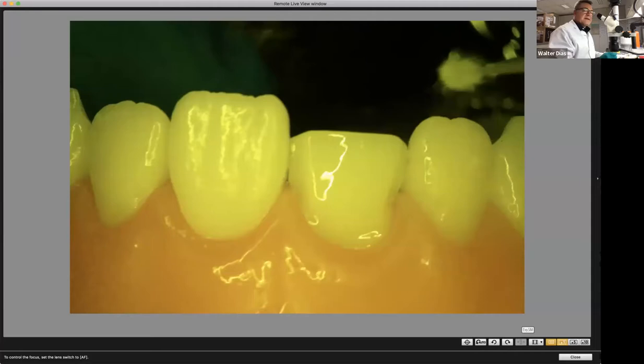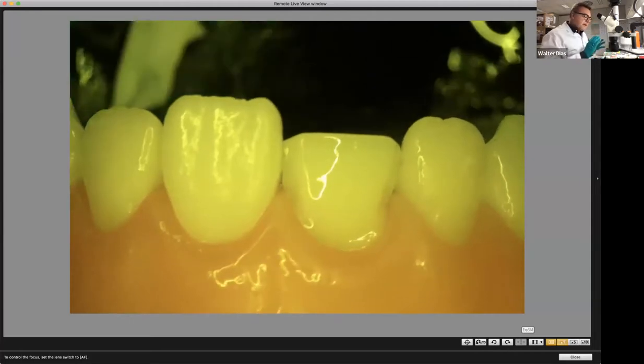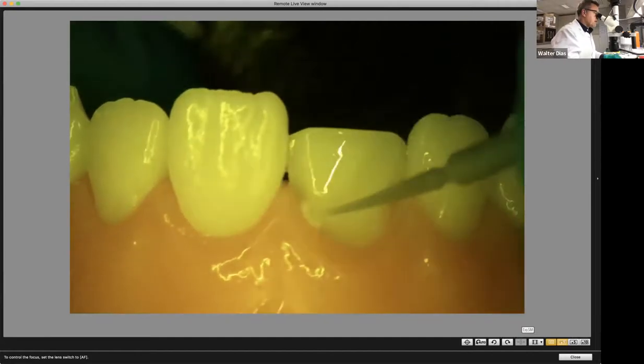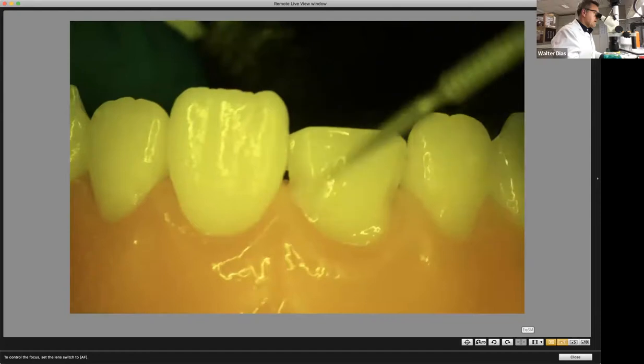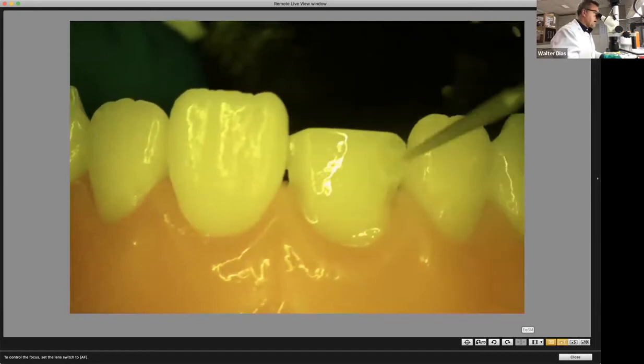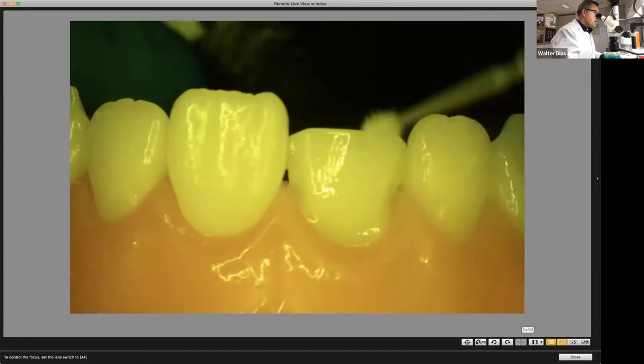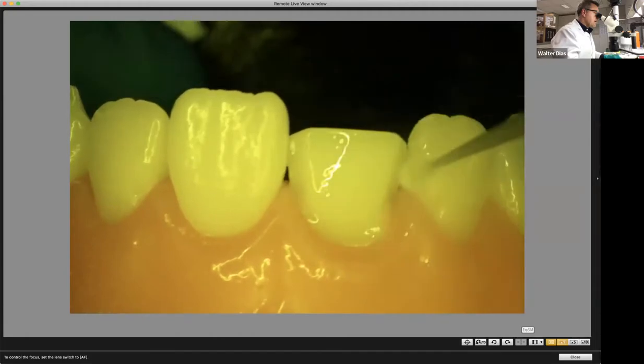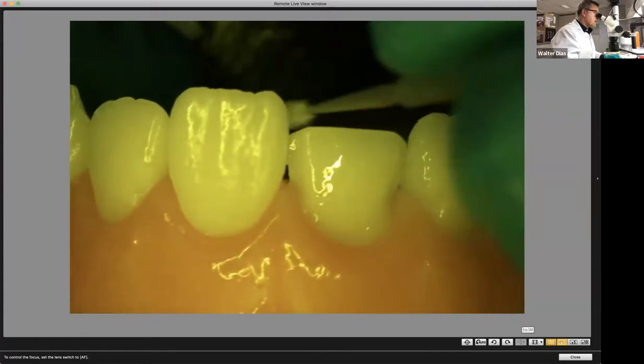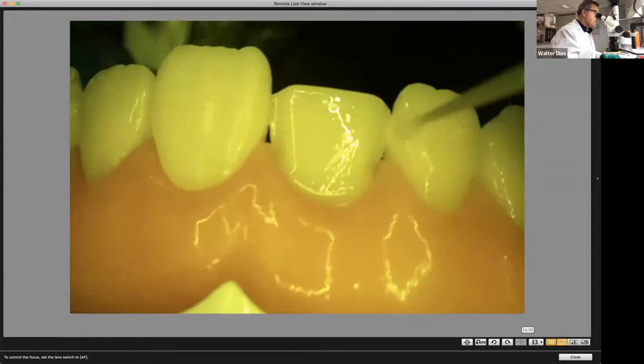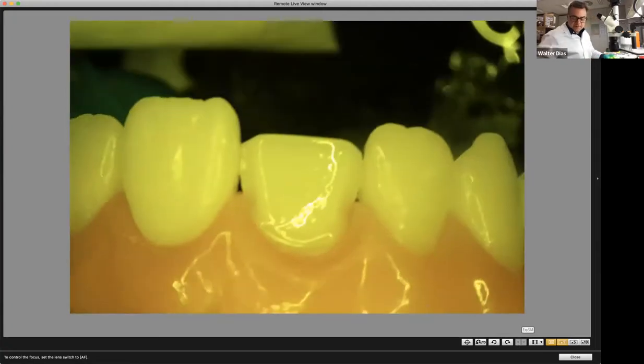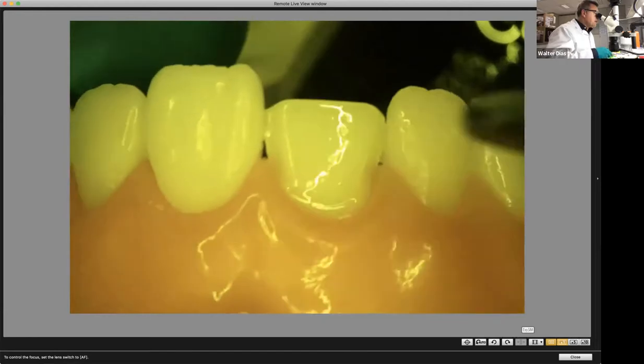So what's going to happen is you can apply, make sure you spread all over, and immediately start removing the excess, because this is just etched enamel and composite. If it is dentin, then you need to observe those 20 seconds. So now you come, especially in the corners, and remove the excess. And in cases like this, you may need a small microbrush. And of course, you're going to need to use rubber dam or a retraction cord. So since you removed the excess, now you can air dry this a little more forcibly.